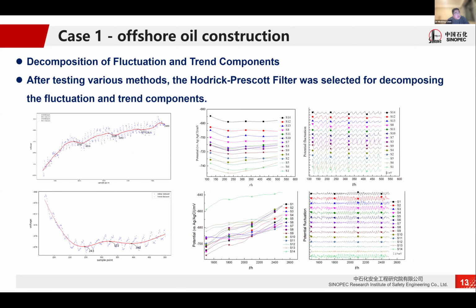In order to extract the effective characteristic peak data, we smooth and filter the results of the open circuit potential measurement and obtain the trend term. Then the fluctuation term is obtained by subtracting the trend term from the open circuit potential monitoring data. The figure on the right is the result of the decomposition. We have tested many filtering algorithms and found that the Hodrick-Prescott filter has the best effect on the extraction of the open circuit potential fluctuations, which are caused by the corrosion environment fluctuations.